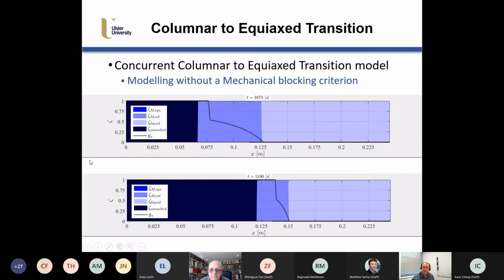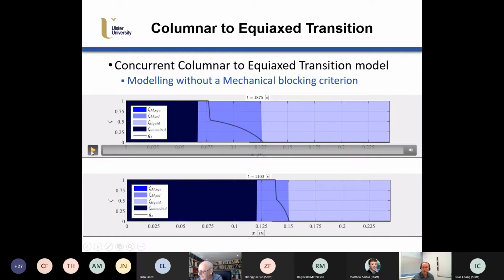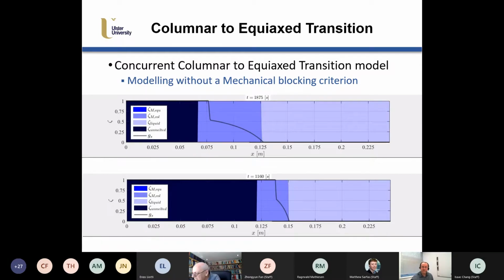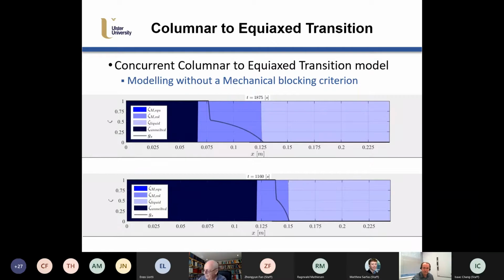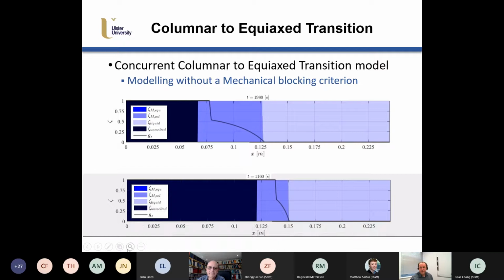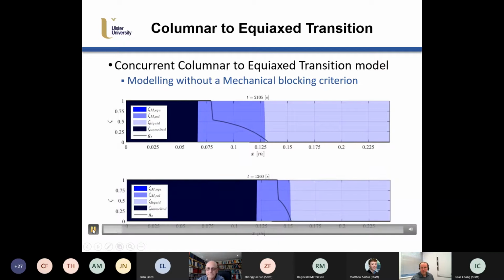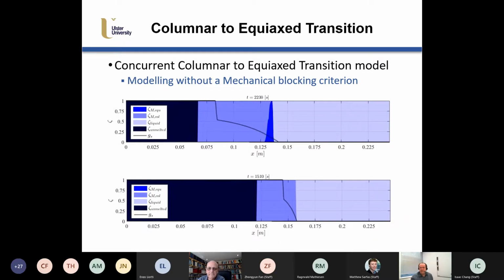And we did a fairly fundamental thing. We said, well, why don't we just completely disband with any mechanical blocking criterion? There's a very famous mechanical blocking criterion by Professor Hunt, and we said we would just try and model this using Kolmogorov principles, which were the principles of the Avrami equation. And so you see here the navy blue that is coming up, or the darker blue, is the equiaxed fraction. So in the case of velocity jump, you see a very sharp transition from columnar to equiaxed.